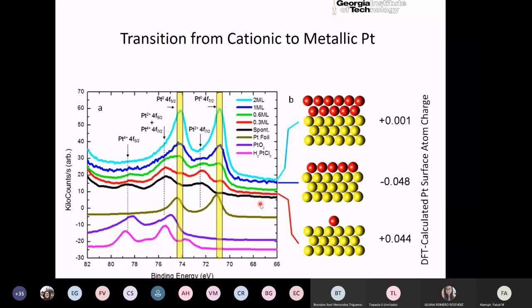What we're seeing down here is the XPS peak position, that is the actual chemical state of platinum and how that is affected by the number of monolayers. And that is basically measuring the electronic effect. And the electronic effect or ligand effect is directly influencing my ORR current. So blue to blue is very highly correlated. But the moment we have the graphene, we lose that correlation. Now you look at the ORR effect and we look at the XPS peak position, and they're not directly correlated to each other. So now we introduce a strain effect coming from the graphene, and it interrupts this behavior.